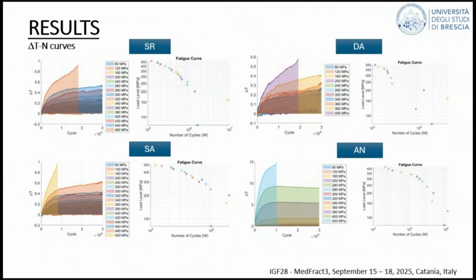Here you can see the results elaborated using the energy parameter that I mentioned before. Now, it has been postulated that if you have a test in which you carry out a series of block testing up to failure, and you take the energy for each block, and then you sum this energy, what you get is a number that in some way is a sort of material property, because it's related to the energy that the material is capable of withstanding.